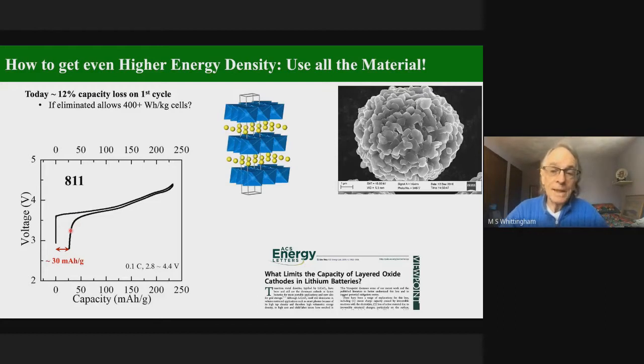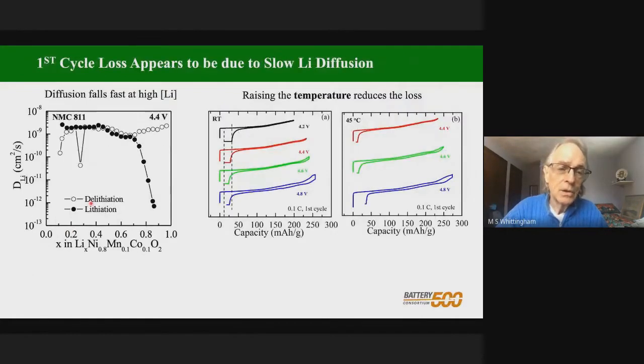So we've been looking at why this occurs, what are the causes of it. And we've concluded that the main cause is low lithium diffusion at high lithium contents. So this is the diffusion coefficient. This is the amount of lithium. And the solid circles is the diffusion coefficient as we put lithium in. So you can see this is pretty constant till we get close to 75% lithium, and then it falls off a cliff. So this diffusion coefficient is dropping by roughly 3 orders of magnitude.